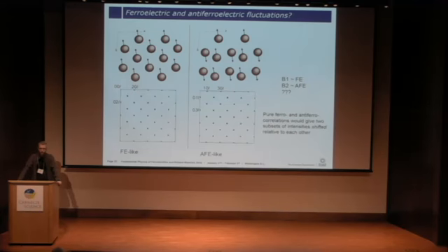Now I go to a hand-waving explanation. If you take a centered lattice, a 2D centered lattice, and you displace all the ions in the same direction, you create the unshifted mesh, like on the left-hand side and like what you have seen for the B1 component.